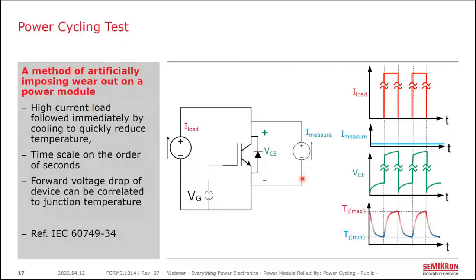I'm not as experienced with the exact value, but the idea is that you're talking something on the order of milliamps here. And the main criteria is that the sensing current can't disrupt the temperature for the measurement. So once you've removed your load pulse that's doing the heating, you don't want to induce further heating with the measurement current. So it has to be low enough that you're not heating the device. It has to be high enough that you can measure a voltage drop in a somewhat noisy environment because you're pulsing this on a test stand over and over again.